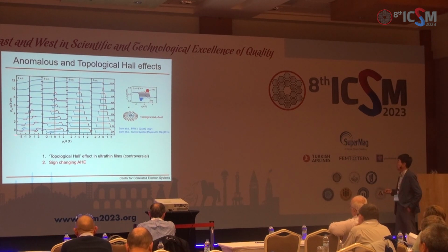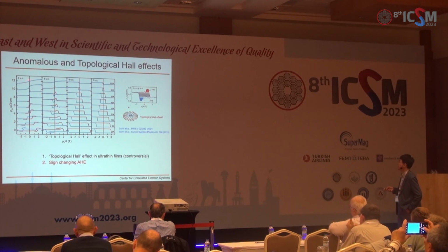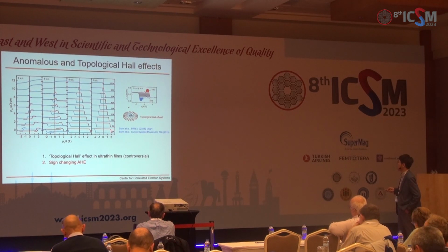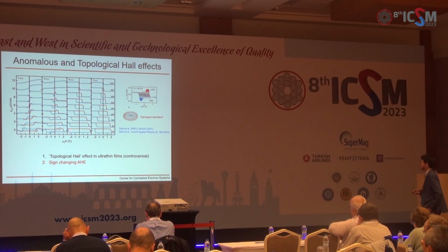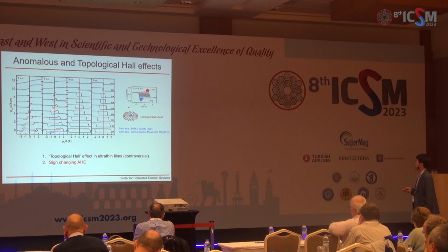Now let's look at some data. Here I show you anomalous Hall effect data as a function of film thickness, so 4 unit cell, 5 unit cell, 6 unit cell, 7 unit cell, and also as a function of temperature. So this is low temperature data, that's high temperature data. You see that anomalous Hall sign here, but also we have some hump structure here on top of this anomalous Hall effect, and we believe that's due to topological Hall effect, and we reported this in these 2 papers.